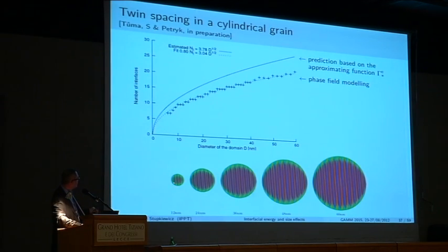Again, depending on the size of the grain, we get the number of interfaces. And this also perfectly fits with the square root function with a little bit different parameter. So the difference is probably mostly due to several issues. The first one is that we use isotropic elasticity to get this, while here we use fully anisotropic elasticity, so one has to do some simple adjustment of the energy. One would, of course, then have the perfect agreement, but we don't do that, not to cheat, say.